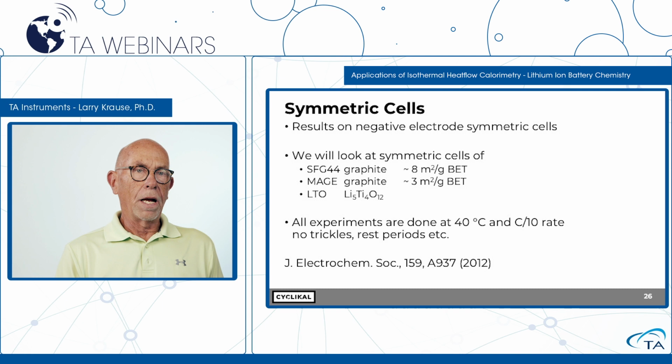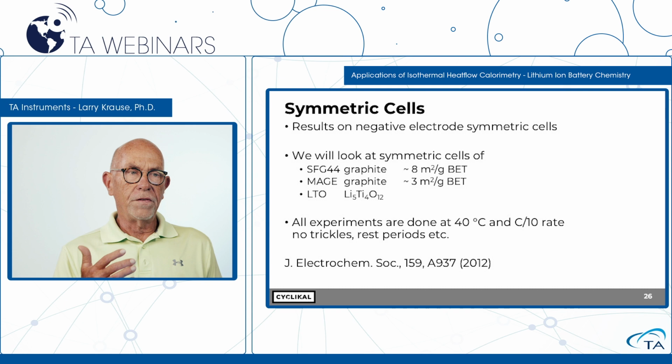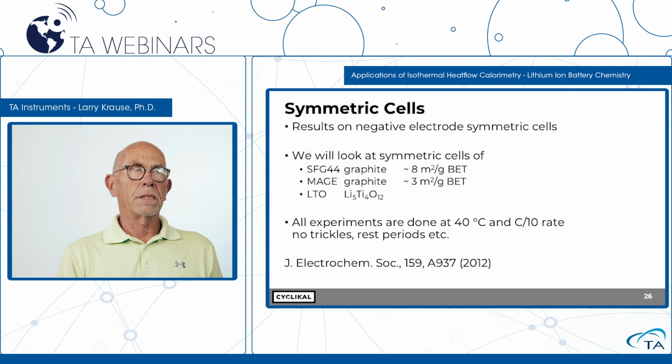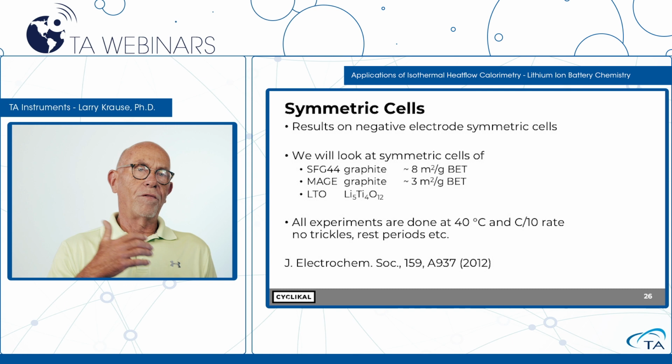But the problem, and why you don't see that in commercial applications much, is the following. Graphite has a potential within 50 or 75 millivolts of metallic lithium. The titanate electrode is, as I recall, up around 1 volt positive of metallic lithium. So if I build a full lithium-ion cell from graphite, I'll have an average voltage of 3.75 volts. If I build one out of the titanate, now it's like 2.5 volts. So I lose a huge amount of voltage by using the titanate, and therefore I lose a huge amount of energy.